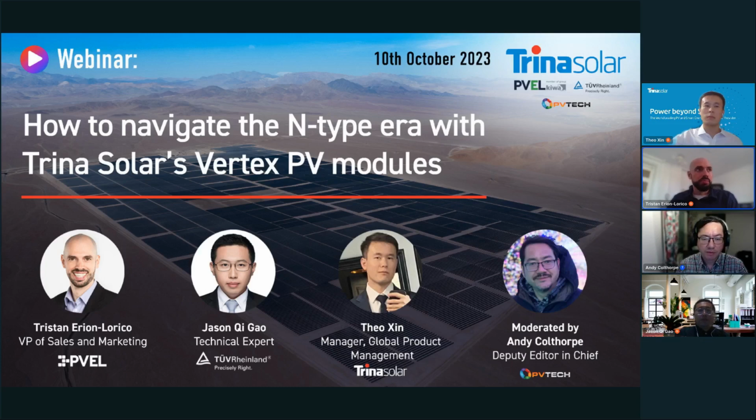Yeah, I can certainly speak to that. We covered that in the scorecard. Basically we're seeing that glass-glass modules break more during hail than glass-backsheet modules. With glass-backsheet, the glass is fully tempered, whereas with 2 millimeter or 1.6 millimeter glass, it's not fully tempered. I think you can probably safely withstand a 30 or 35 millimeter hail impact with glass-glass modules. But once you get up to 50 millimeter hail impact, the failure rate on glass-glass is about 90%, and on glass-backsheet, I think it's about 35% fail. So the majority of glass-backsheet modules can pass that 50 millimeter hail.